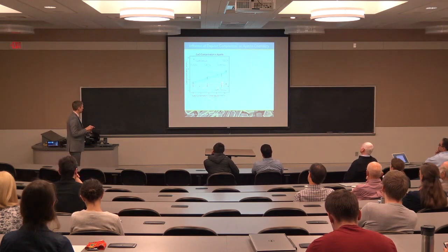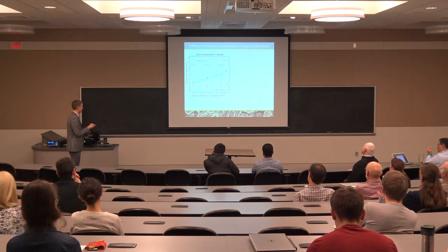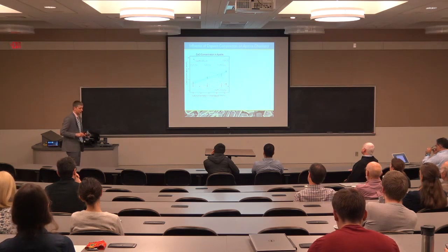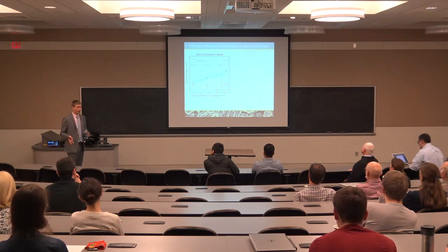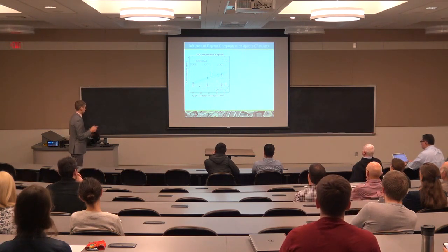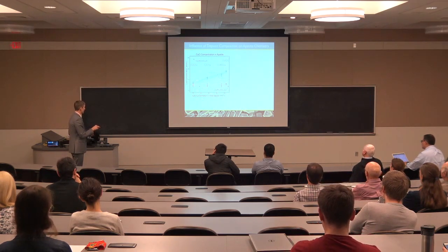We can also look at the composition of the apatite. When we do the experiments just with pure rare earth oxides, either yttria or gadolinium, the apatite composition is basically constant if we look at the calcium content. And this composition right along here corresponds to this defect-free structure where we don't have to incorporate any vacancies to form the apatite. Now, when we do the experiment with zirconia in the system, we find that as we increase